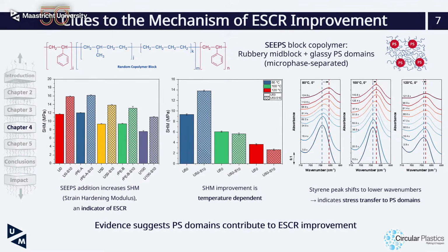modulus. A strain hardening modulus is a very well-known indicator for slow crack growth and ESCR in the literature, and it works very well for virgin material. It also has an ISO standard, and it's measured from the slope of a strain hardening region in tensile test at elevated temperatures. When we check the strain hardening modulus results for HDPE grades and for the blends with SEEPS added, we see significant increase in strain hardening modulus.